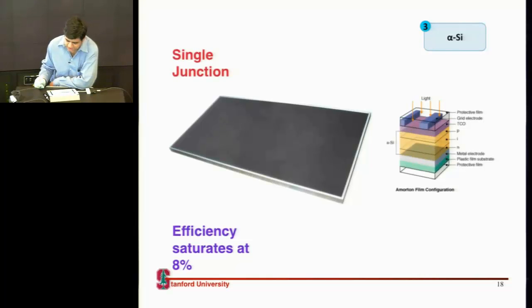So if you try to make this amorphous silicon cell, the band gap is 1.7, you might be thinking, I'll get an efficiency of 20-30%. On the very best day, on the very first day you test the cell, your efficiencies are like 8 or 9%, because there are so many defects inside this amorphous silicon.